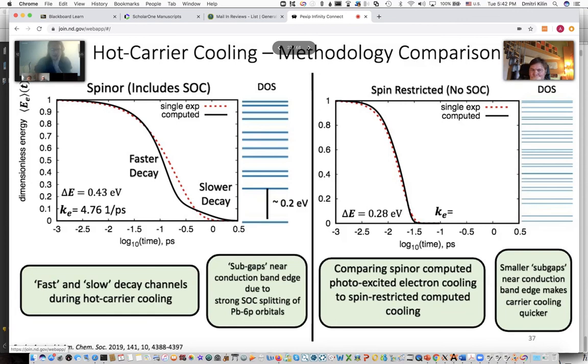And then to drive home the point of how important spin-orbit coupling is to accurately describe the dynamics in these materials, I compared the decay with spin-orbit coupling to if we did not include spin-orbit coupling, or just used spin-restricted DFT. So on the left figure, we see that there seem to be two decay modes. There's a faster decay, and then it slows down as it gets closer to the band edge, or gets closer to its lowest energy state.